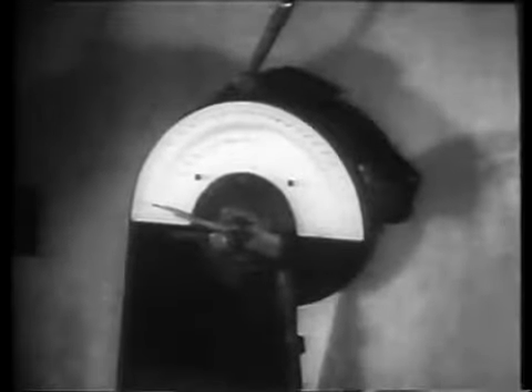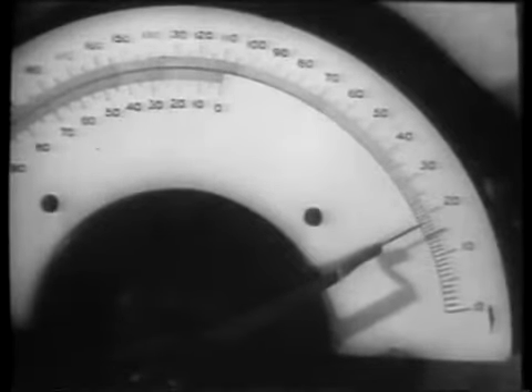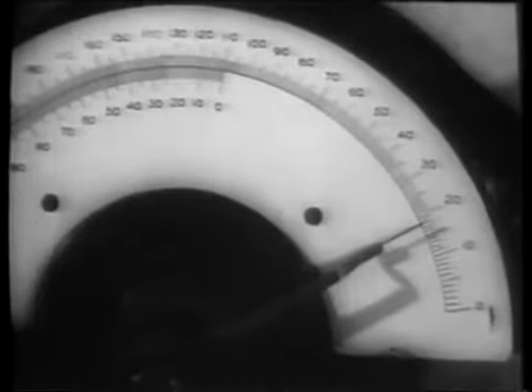When we speak of toughness, we need a quantitative guide, an accurate means of measuring it. The Charpy Impact Toughness Testing Machine answers that need. It determines the resistance to impact offered this pendulum by a specially prepared specimen bar of the steel under test. The specimen is placed across the pendulum's line of travel. The pendulum is drawn back to a fixed angle. When the pendulum is released, the energy required to break the specimen reduces the swing of the pendulum. This dial registers the pendulum's travel. It measures in foot-pounds the energy required to break the test piece. This is a measurement of the steel's toughness.